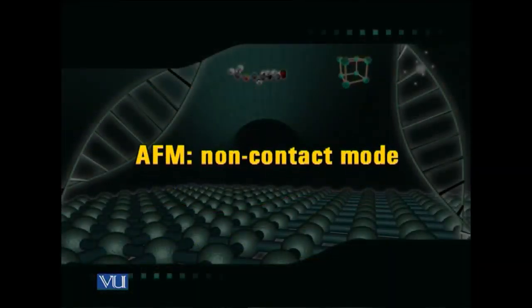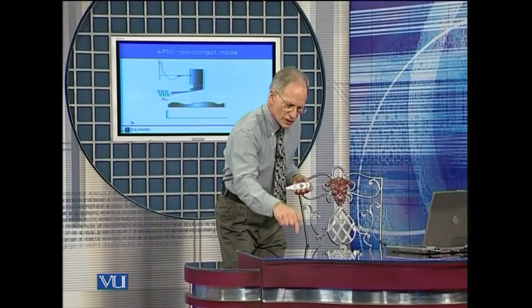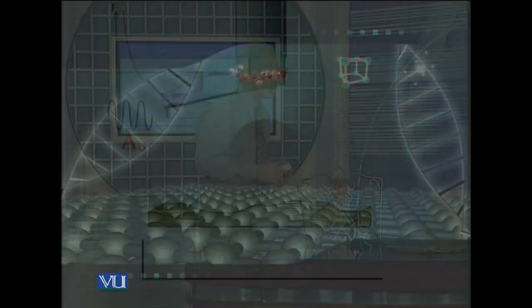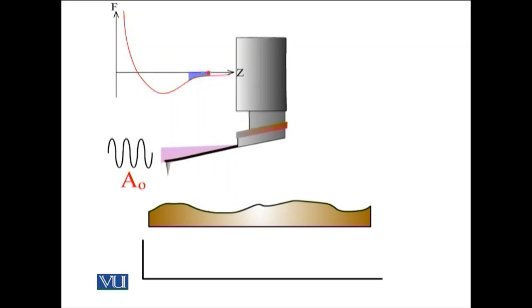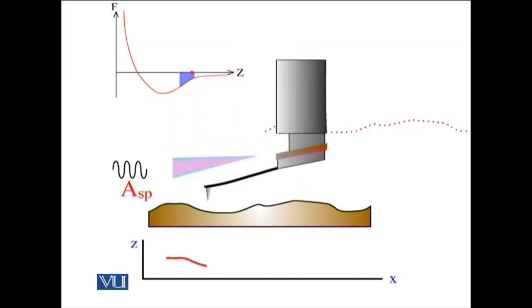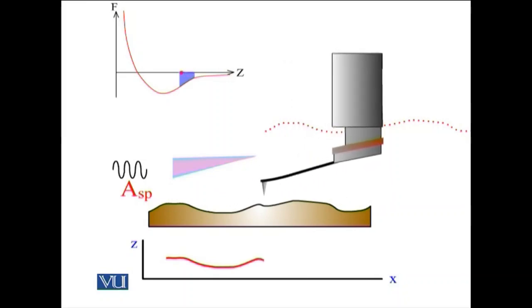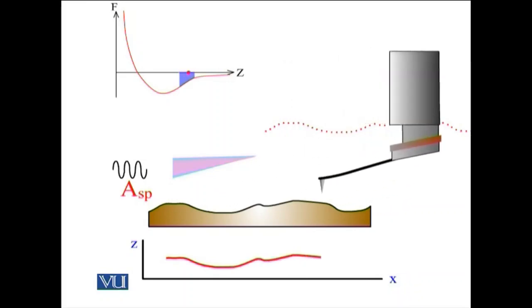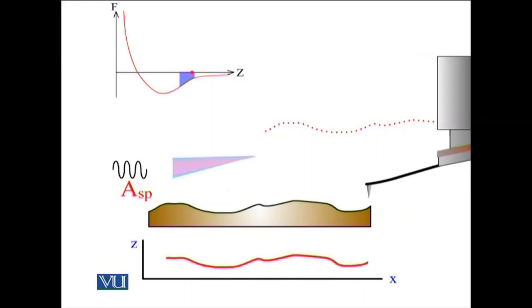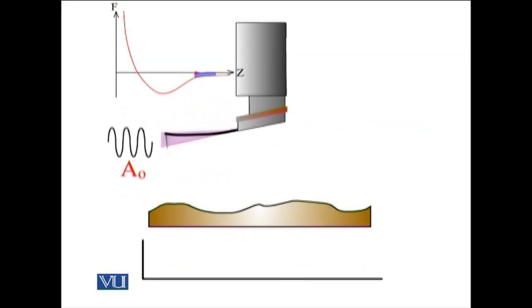surface. If I've got something on it like that, I can move it away, and I don't want to do that. So instead, I'll come up with a slightly different technique, and now I'm going to be moving like this, coming closer and backing off. As I'm far away, I have a particular vibrational frequency. As I come closer and start sensing the potential of the surface, the frequency changes. And I say, good, stop, no closer, let's stay in that mode. So there we are at one mode.